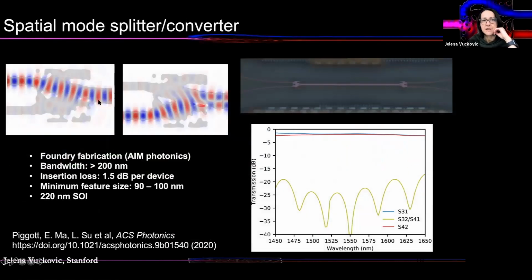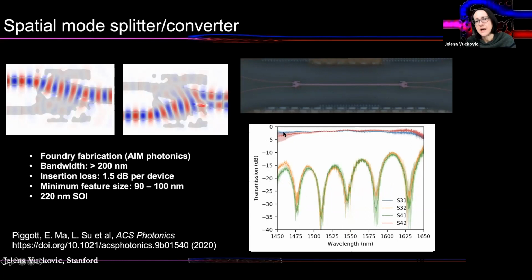Then here is another one, a spatial mode splitter converter. You split the first order mode and send it to one port. This is about a 2.8 by 2.8 micron footprint. The second order mode is converted to the first order mode and sent to the other port. We fabricated a cascade of these two in a foundry. This is the theoretically predicted behavior. And this is important for, again, optical interconnect systems and capturing both polarizations from the input fiber in order to increase the communication capacity. And here is the theoretically predicted behavior, and this is the measured behavior for many of them. And they all line up, again, on top of each other without any post-tuning.